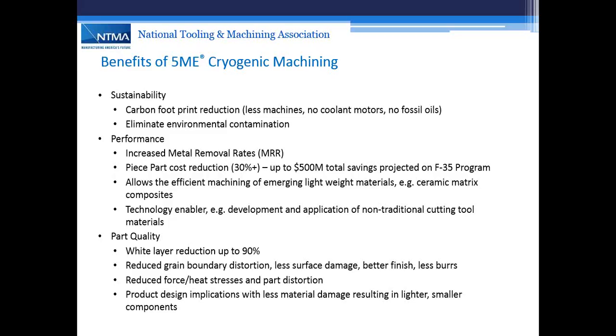When you start looking at metal matrix and ceramic matrix composites, all of those are either very hard to machine, high temperature alloys, or extremely abrasive materials. Again, by keeping the heat out of the cutting tool, you will be able to reduce the heat that comes with the high abrasion and heat resistance of these materials. It's also a cutting tool enabler. There are some cutting tool materials that are normally not used. For example, we've been able to apply diamonds to titanium. Normally that's not applicable, but when you extract the heat and allow the diamond to stay in the diamond state rather than regraphitizing back to carbon, now you can get significant tool life and speeds with diamonds where you normally could not.